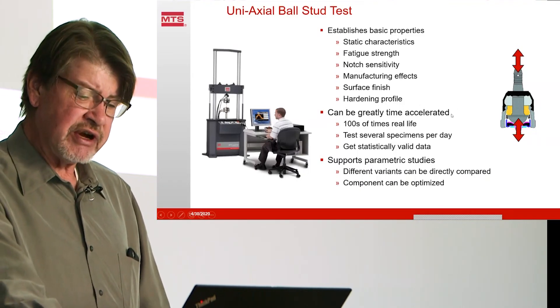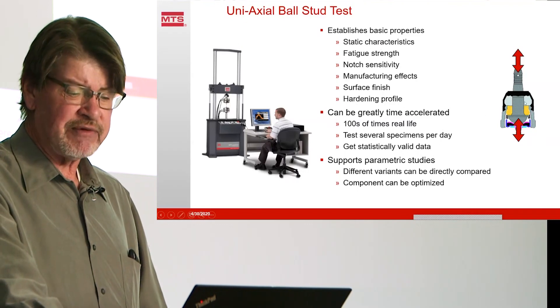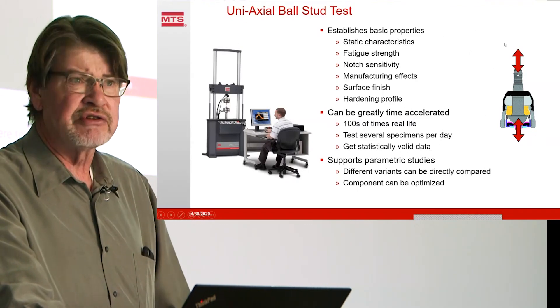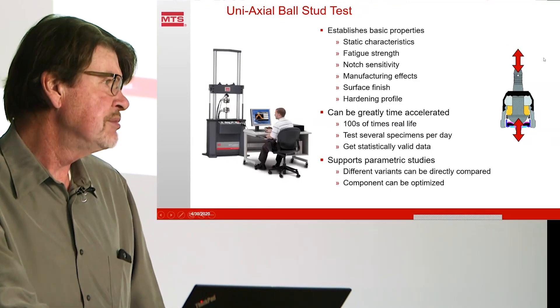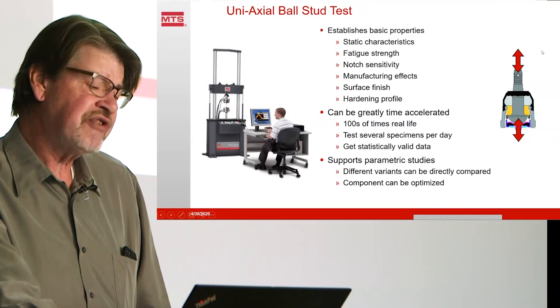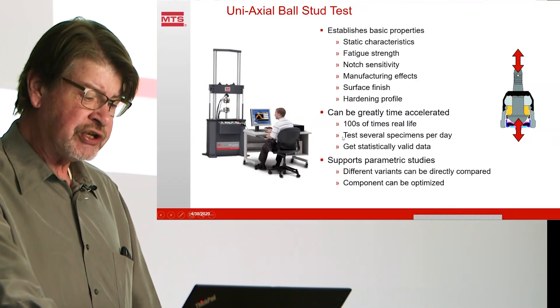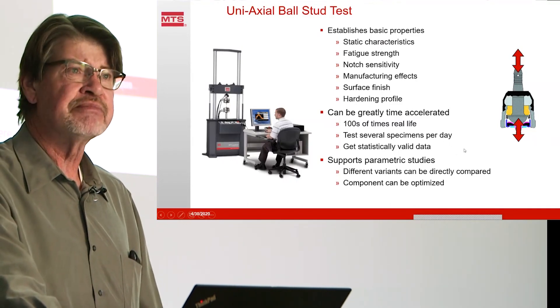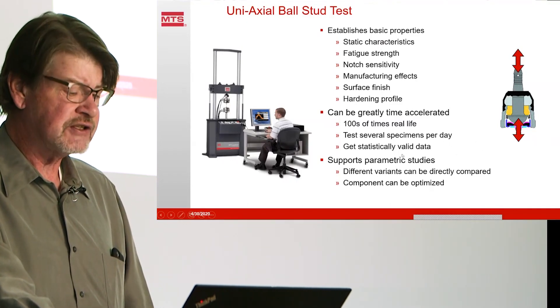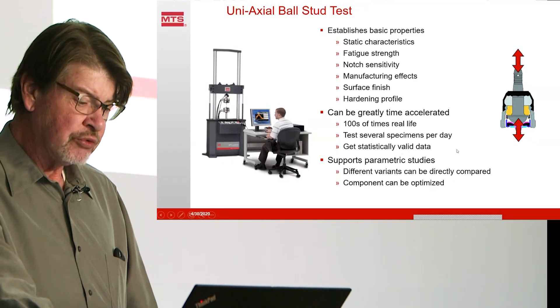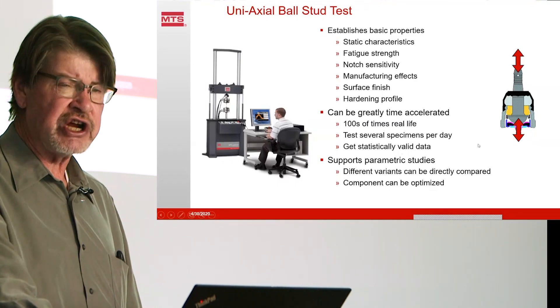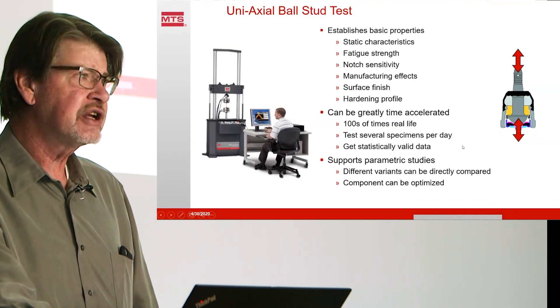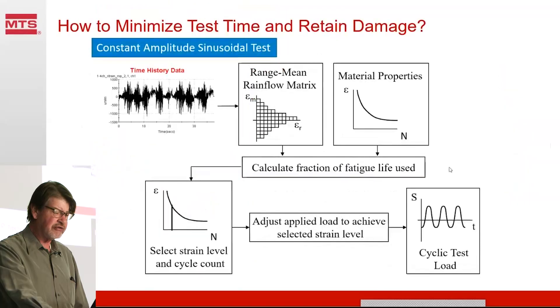We can greatly time accelerate that test. Maybe we were testing an equivalent of 15 Hz on the road — we can test it at 50 Hz or 100 Hz, be 10 times faster in the laboratory. We can test several specimens per day and get statistically valid data by comparing the results from very similar tests. We support parametric studies. We can change one parameter — maybe a radius or a hardness — and then test again and compare directly the difference in life.